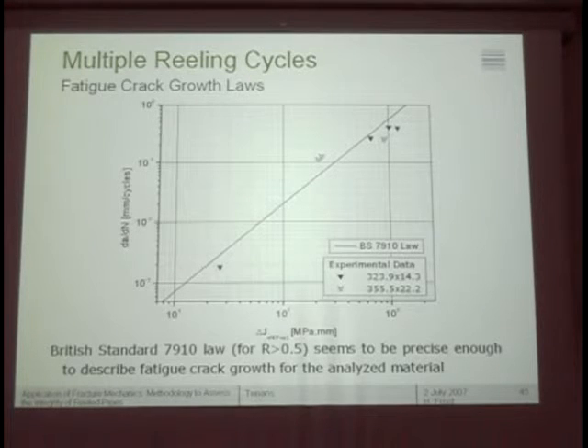And this is basically the type of result that we got in terms of the dA/dN versus delta J effective, as I mentioned before, using the crack closure effect and so on. This is a best fit line, except that it comes from the British standard 7910, so it's really not the best fit line. It's the one coming from the standard, applicable for R bigger than 0.5. That means when we consider the whole cycle is completely open, if you prefer. The opening is lower than the mean, so this is basically good for the whole cycle, which is consistent with using delta J effective. So we were pretty surprised to see this.